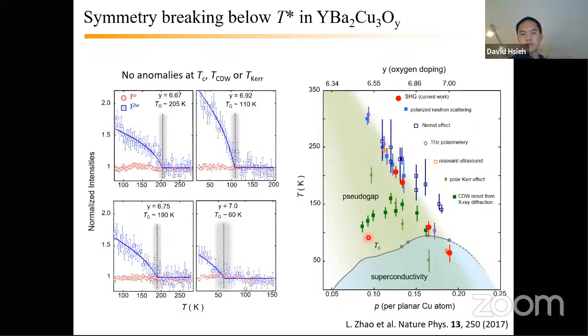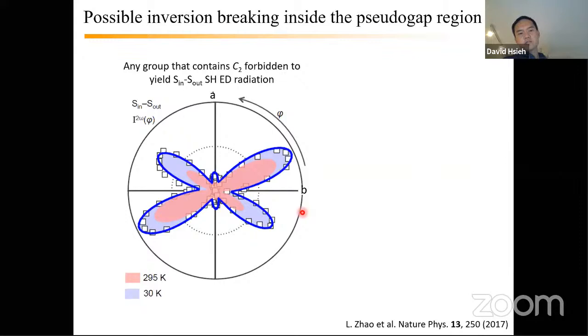The way we had to interpret this data is a bit tricky because, as you can see, here I'm overlaying the patterns both above and below T star on top of each other. Below T star, there's a change in intensity, but there's no change in the apparent symmetry of the pattern, right? It still looks like this sort of 2 over M type pattern.